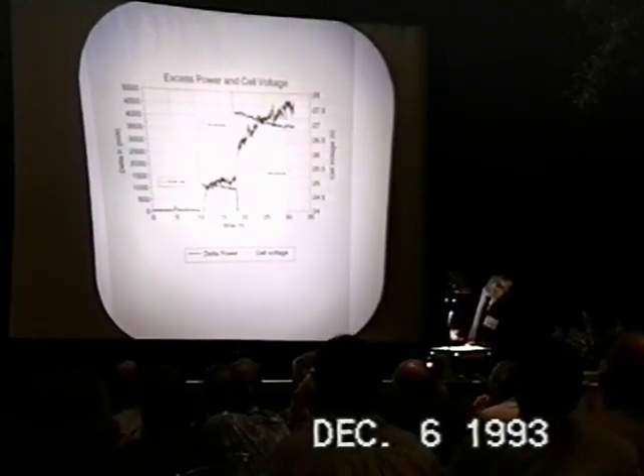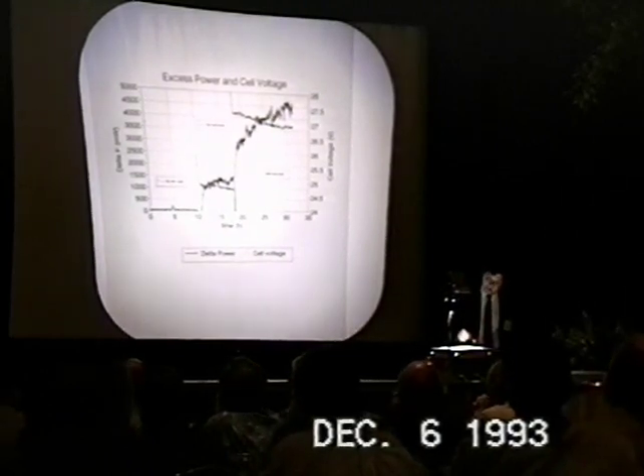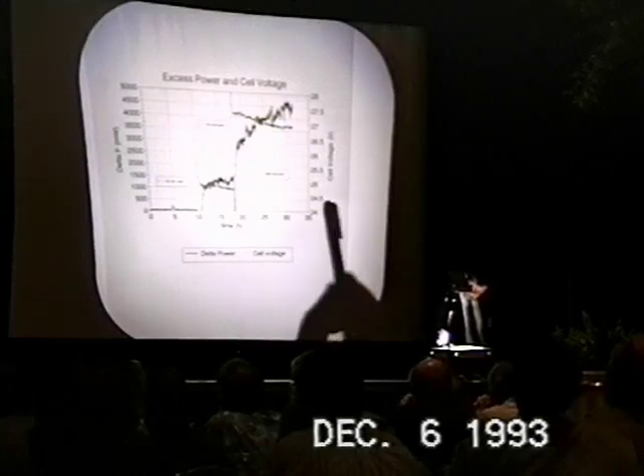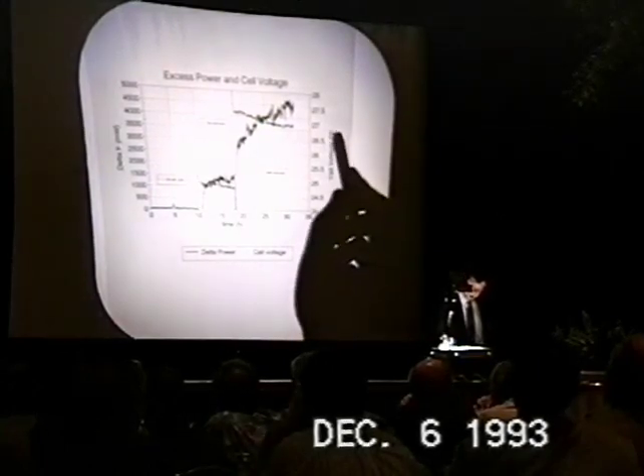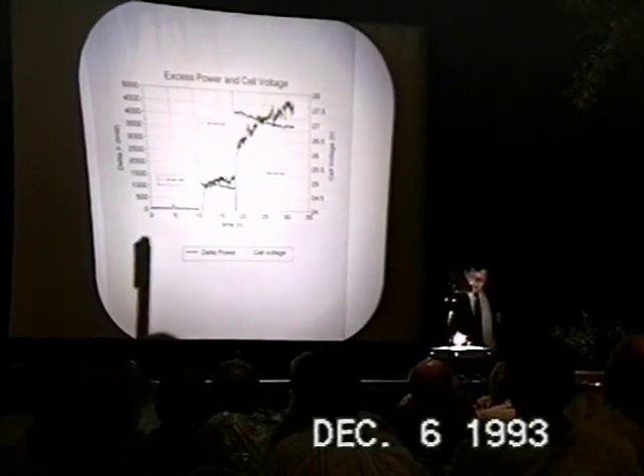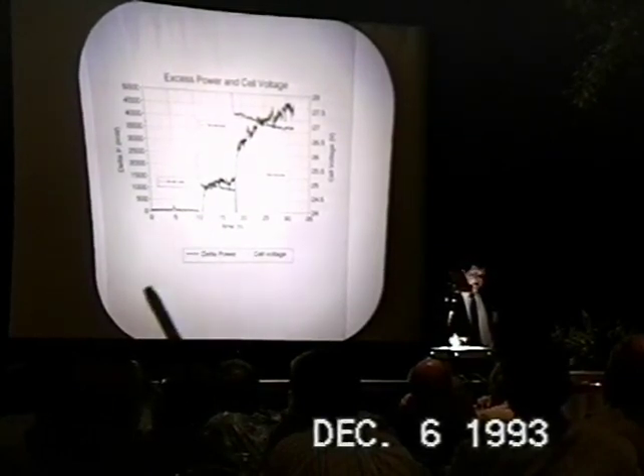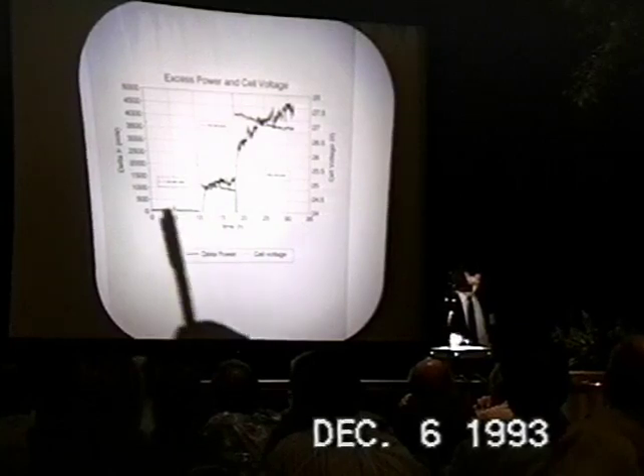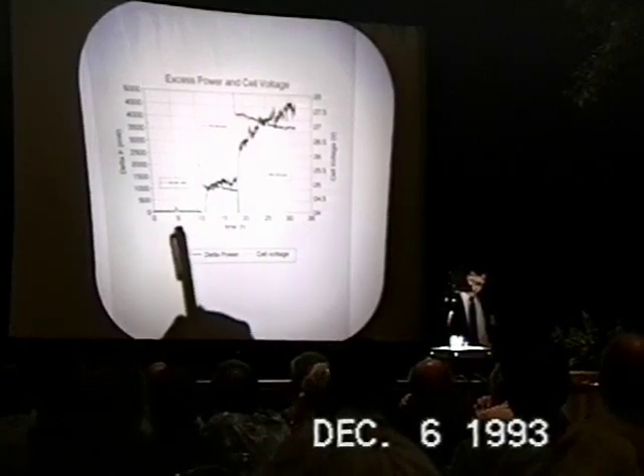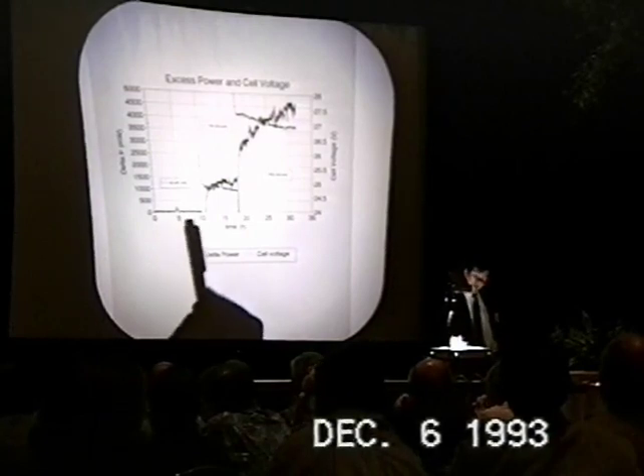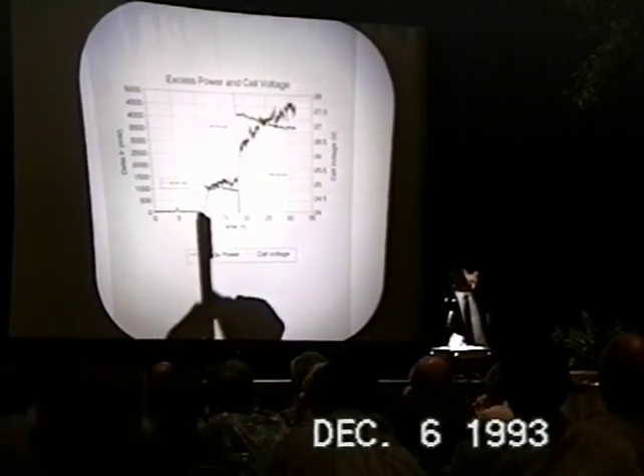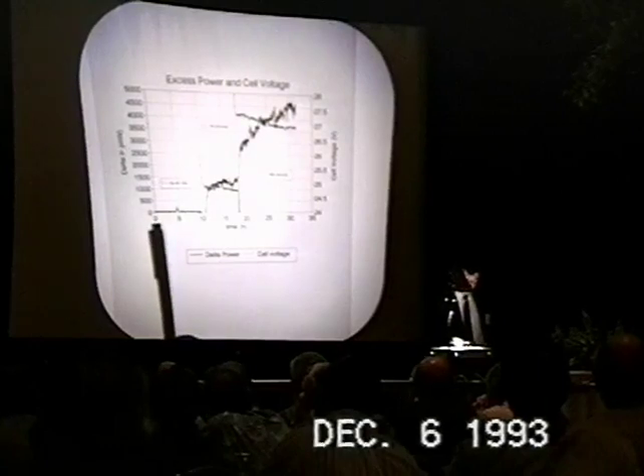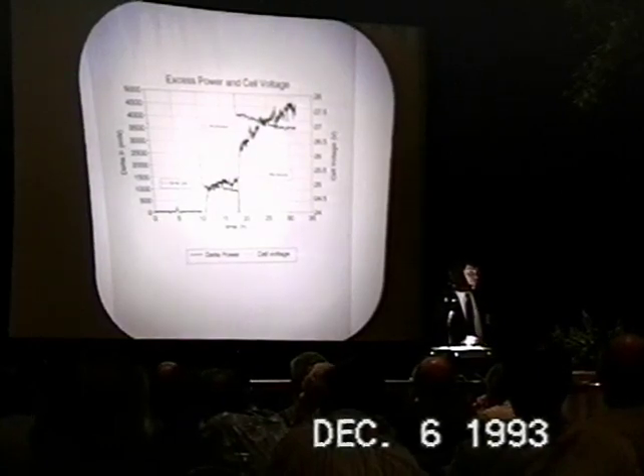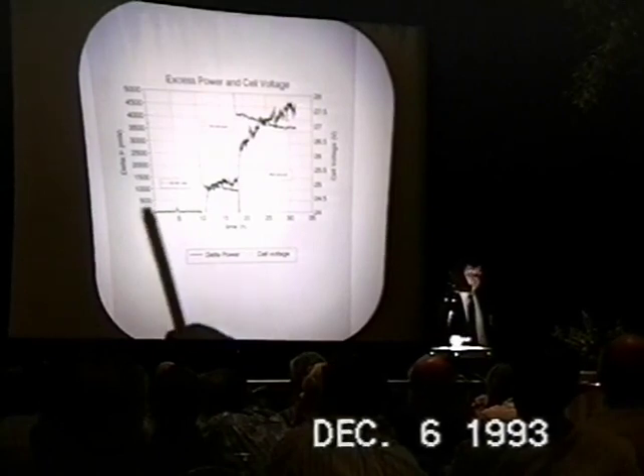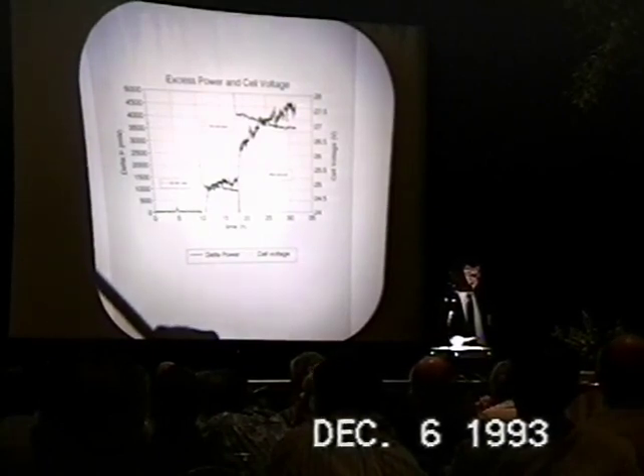The experiment lasted a long time, almost 1 month, and I'll show you the latest hours. Here on the left we have the delta power, and on the right we have the cell voltage. During the first 10 hours, we had a constant current, about 50 milliamps, and we saw just a little amount of heat production. We already saw heat production the days before.